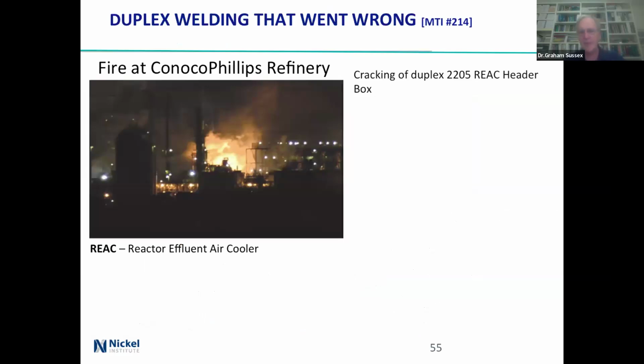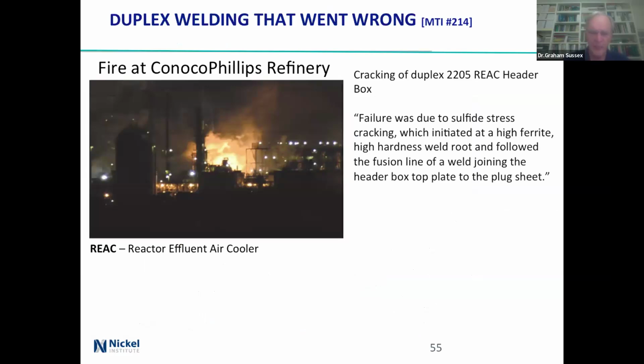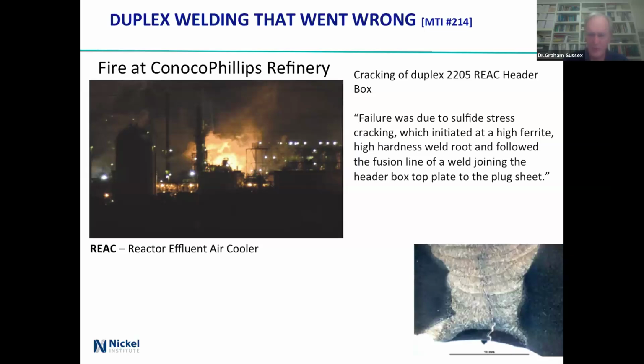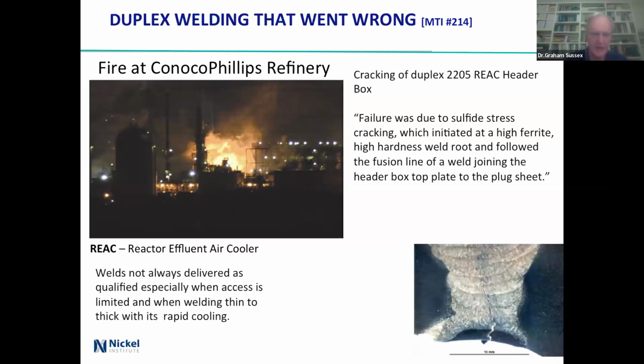Okay, this is a failure investigation at a reactor effluent air cooler. And there was duplex 2205 being welded, sulfide stress cracking because high ferrite, high hardness weld root, because it was welded to something that was relatively thick and it didn't give you adequate heat. And so you wound up with a problem and a big fire.